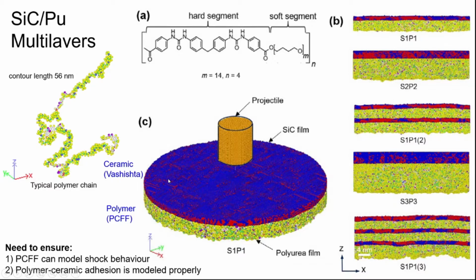We use the Vashishta potential to model ceramic and PCFF to model polymer. The Vashishta potential has been specifically developed for silicon carbide, and it has been demonstrated that the potential accurately reproduces experimental shock Hugoniot of ceramic. In contrast, PCFF is a non-reactive potential and it has not been previously used to study the shock behavior of polyurea, and therefore we need to validate the PCFF before we use it to model shock behavior of polyurea.